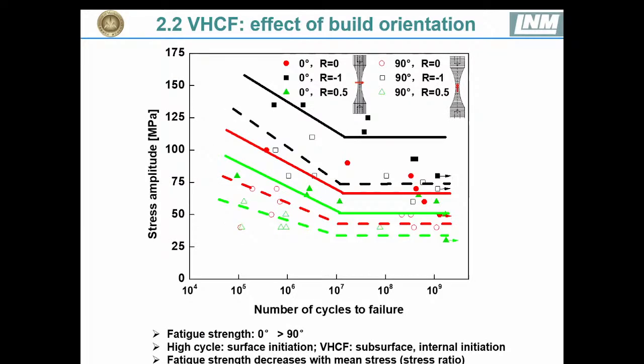And then we come to the very high cycle fatigue property of the specimen manufactured at a different build orientation here. And from this figure, we can see that fatigue strength for the specimen manufactured at 0 degree is larger than that with 90 degrees. This is in agreement with the tensile property, which we showed before. And here we can see that the fatigue strength decreases with mean stresses. This is the mean stress effect.